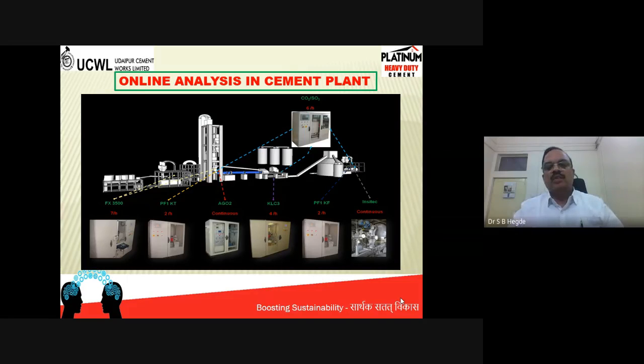And the third box is the online free lime analyzer. Free lime is nothing but the residual lime left over after the reaction of lime with silica, alumina and iron. Whatever leftover lime there is, is called free lime, and free lime content is very important because it decides the quality of cement. You must be aware that if free lime is on the higher side, say more than 3% or 3.5% in the cement, it will cause expansion of the cement. And you can see in plasters or in concrete the expansion and so many cracks being developed because of the higher content of free lime.